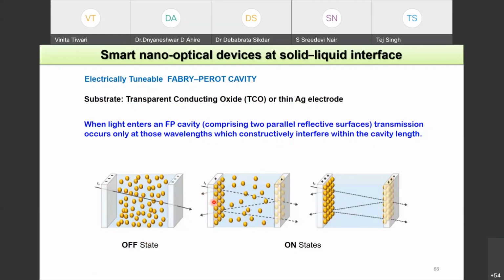Now, what happens when you apply some positive potential to the electrodes? So then the nanoparticles will get attracted to the electrodes and they will start forming a 2D array on the electrode. And immediately the reflectivity of these cavity mirrors will change. So from transparent walls, they are now slowly becoming mirrors, and this will become like a cavity. So you are actually having a cavity in formation. So as the cavity gets formed, then this will allow only those light or those wavelengths to get transmitted, which are satisfying the Fabry-Pérot resonance condition.